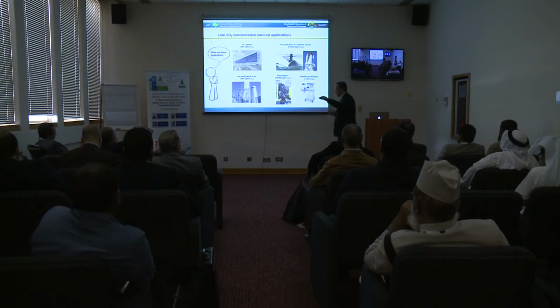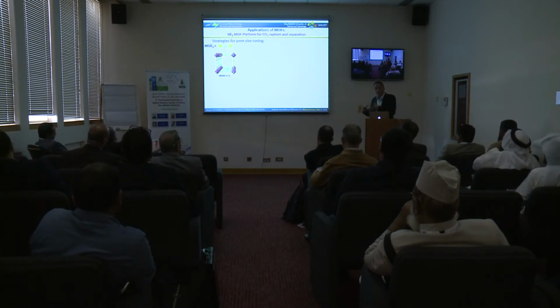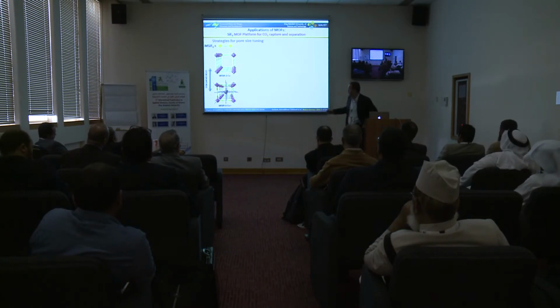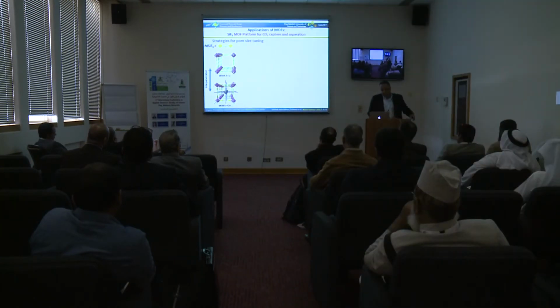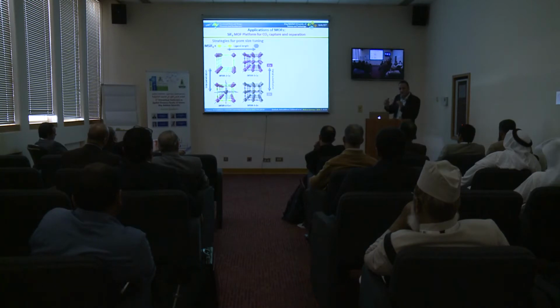Now I will show you a list of results where we apply this to metal organic frameworks. First of all, this is a system just to show you that by using, for example, this kind of metal organic frameworks, we have a control over the pore size. First of all, we can just make 2 networks, one inside of each other. This is a metal, can be copper or zinc, SiF6, which is an inorganic hexafluoride silicon. Then this is bipyridine type ligand. You can see here that you can reduce the pore by interpenetration. Or you can use shorter linker with copper, for example, or you can change the metal, copper, zinc, and so on. Here I'll show you just by tweaking a little bit of chemistry, we make something that has very interesting properties.